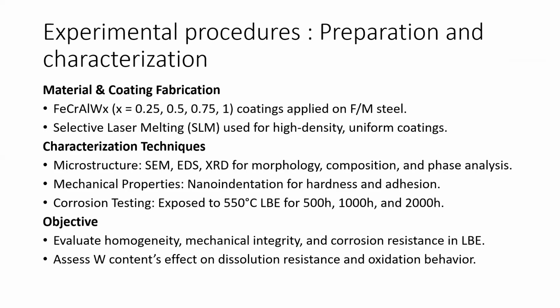For the characterization techniques, to see the microstructure, we use SEM, EDS, and XRD for morphology, composition, and phase analysis. For mechanical properties, we use nanoindentation for hardness and adhesion. And for corrosion testing, we expose the coating to 550 degrees Celsius LBE for 500 hours, 1000 hours, and 2000 hours.